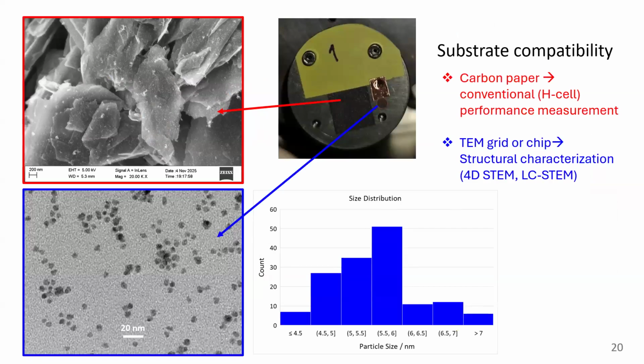And so in terms of the characterization, the technique is also very amenable to high throughput characterization, in that we can sputter and deposit nanoparticles on virtually any substrate. So for example, typically when we're measuring bulk electrochemical performance, we're doing this in what's called H-cell measurements, where we deposit our particles on a carbon paper in order to have high electrode area in order to measure product selectivity using gas chromatography. And so for that, we need high surface area electrodes.